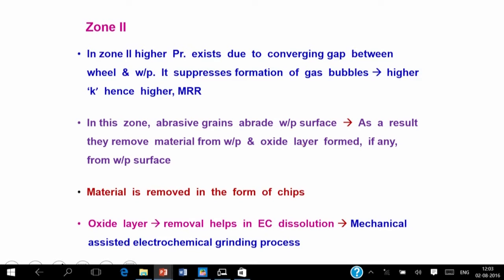Oxide layer removal helps electrochemical dissolution, because in any electrochemical or chemical process, passivation layers are generated. This passivation layer has to be removed to make the fresh metallic surface exposed to the electrolyte. As the abrasive particles remove the passivation layer in zone 2, fresh metal comes out in front of the electrolyte, so more machining will be there. That's why it is called the mechanical assisted electrochemical grinding process, because here more material is removed in zone 2 by electrochemical dissolution and also by the mechanical grinding operation.